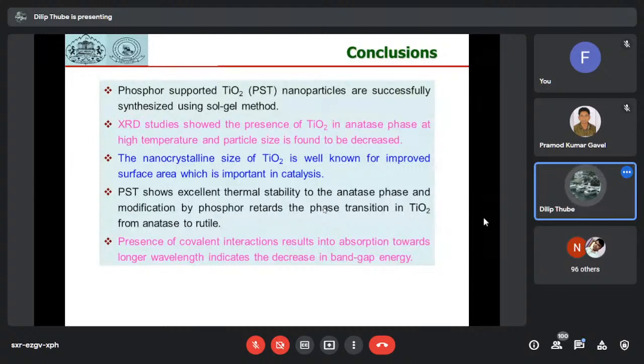The important conclusions from this project are: phosphor-supported TiO2 nanoparticles have been successfully synthesized by using a simple, low-cost sol-gel method. XRD studies showed the presence of TiO2 in anatase phase even at high temperature, and the particle size is found to be decreased. The nanocrystalline size of TiO2 is well known for improved photocatalysis. Phosphor-supported TiO2 shows excellent thermal stability of the anatase phase, and modification by phosphor retards the phase transition in TiO2 from anatase to rutile.